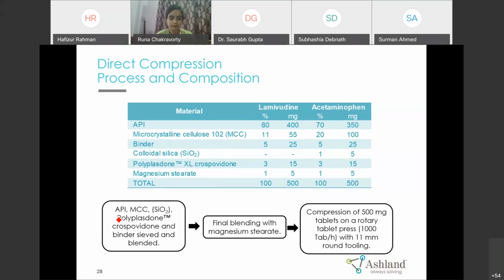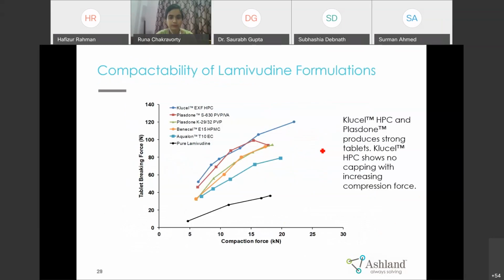So what we have done, we blended API with diluent and other ingredients. Then we lubricated it with magnesium stearate, and we compressed tablets of 500 mg. Similarly, in case of acetaminophen, we have taken 70% API. Again, binder concentration we have taken 5%, and blended in the same way which I explained. So then we have compressed tablets at different compression force and checked the tablet hardness.